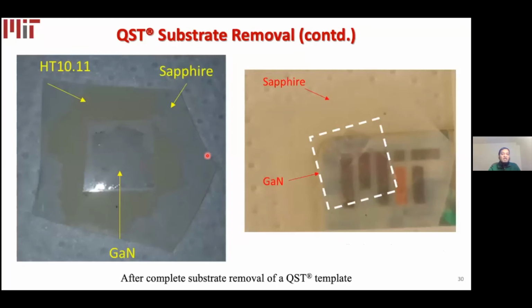This is one example from when we were developing the process. Here on the left, we have the sapphire carrier used for this substrate removal process, and the temporary bonding material HT1011. And this is after complete substrate removal. We can see that it's ultra-thin gallium nitride, about 10 micron thick, remaining on the carrier. And since it's a wide bandgap material, it's completely transparent, as we can see on the right-hand side.